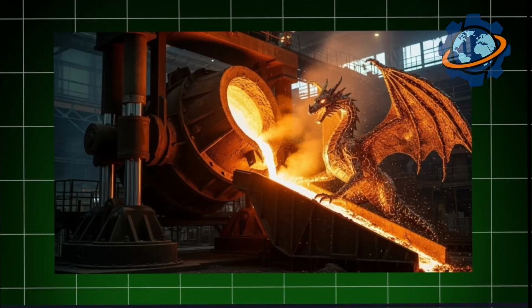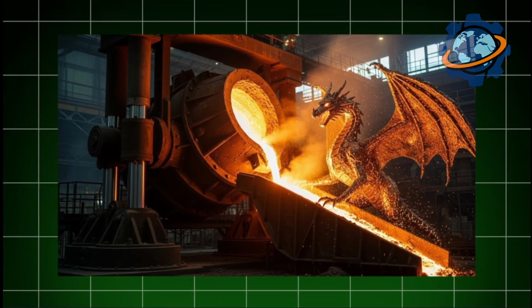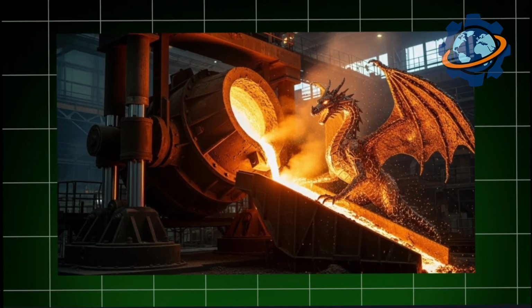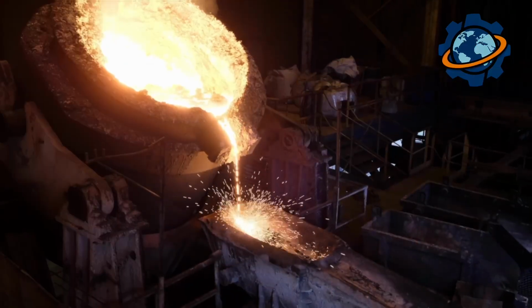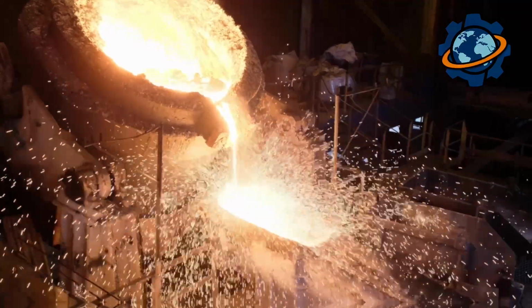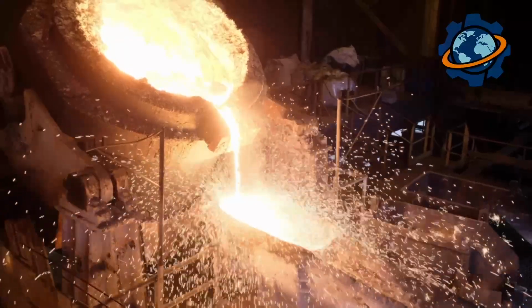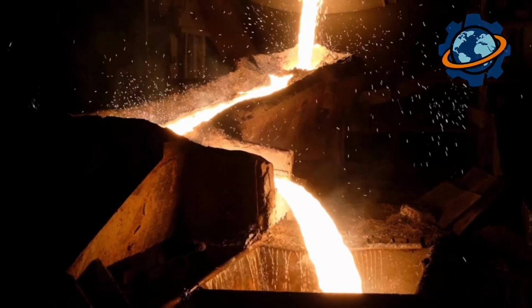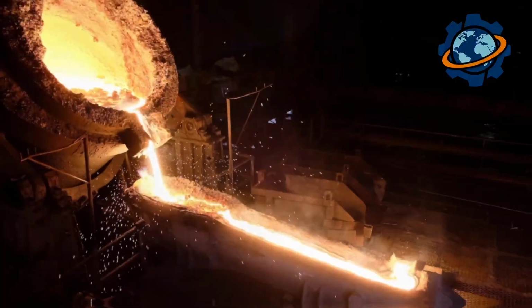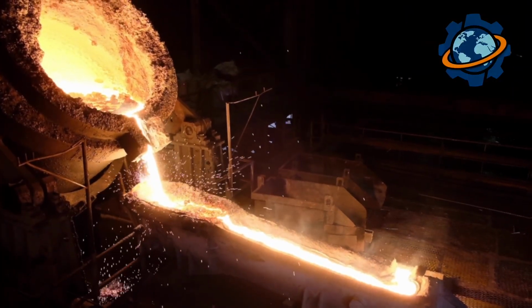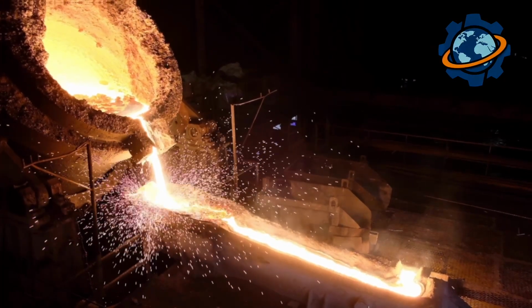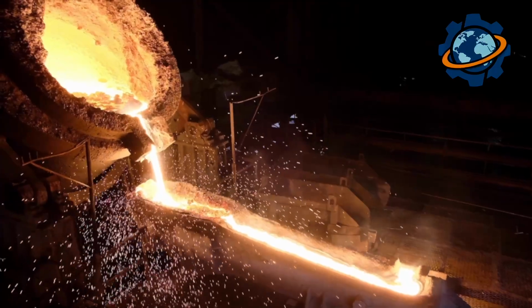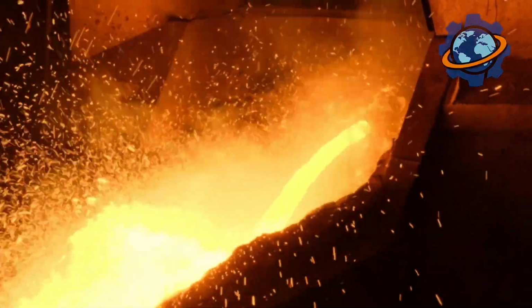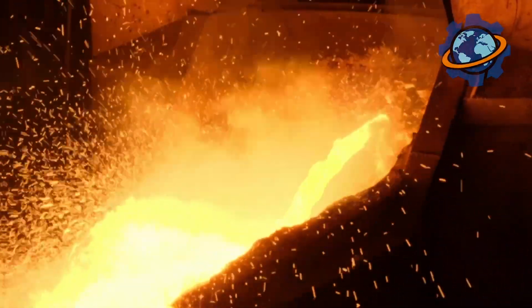Tapping releases the dragon. The furnace tilts hydraulically, massive vessel rotating on trunnions. Molten steel pours through tap hole into waiting ladle. Refractory-lined bucket containing 40 tons of liquid metal. The pour takes 6 minutes. Continuous stream of glowing steel creating updrafts so powerful, they lift dust and debris into the air. The temperature, 3,050 degrees, radiates heat felt 200 feet away.